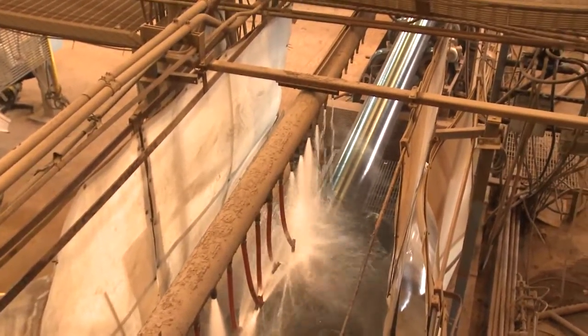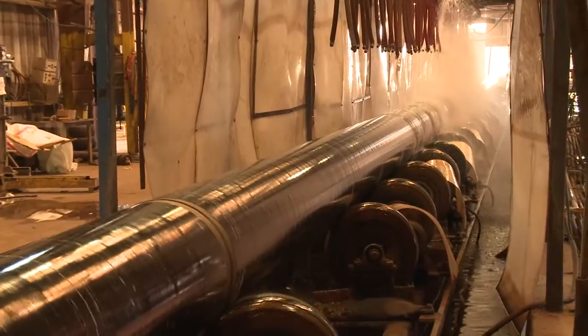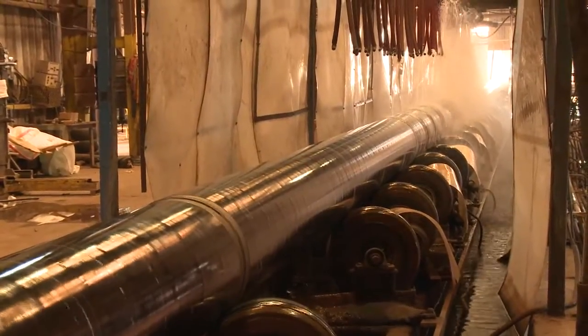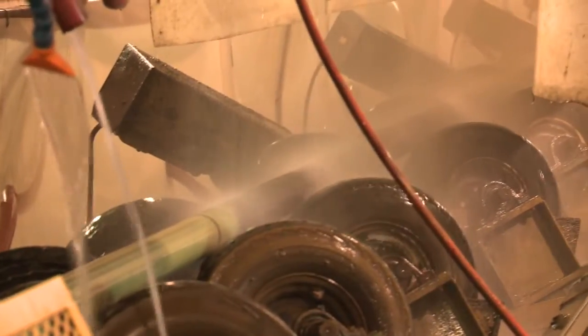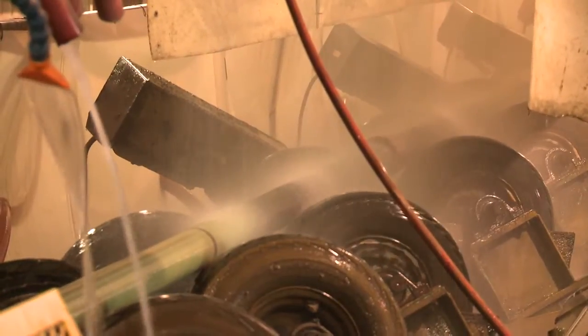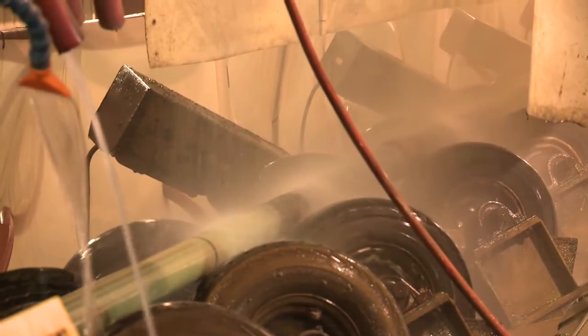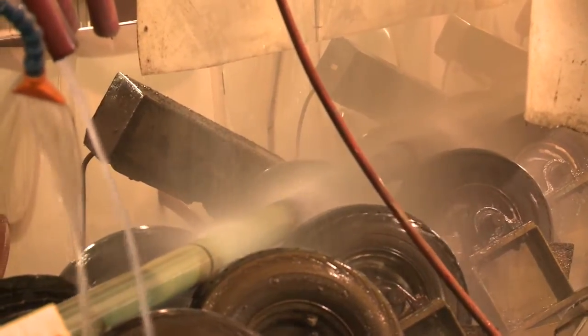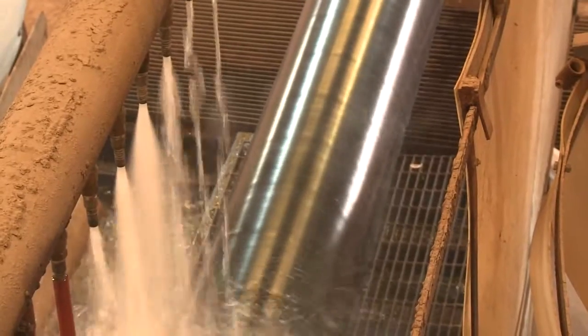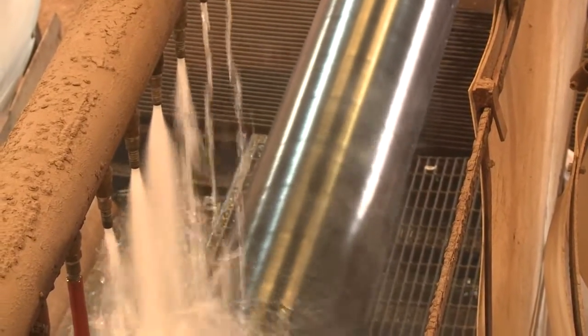The gel time is the time that the powder takes to become tack-free. If the pipe were to get onto the conveyor tires before the gel was complete, it would come off the pipe onto the tires, creating rejects. This would then cause downtime to stop and clean the conveyor line.